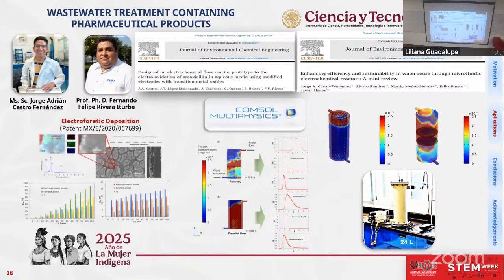So additionally, the title of my presentation is to involve modified surfaces. You can see here how we construct these surfaces, including iridium dioxide and tantalum pentoxide. The iridium is the electrocatalyst to remove the different organic molecules, and the tantalum pentoxide is important to promote protons close to the surface. When we promote protons close to the surface, it generates more oxidant agents like hydroxyl radicals. It's actually very important in the different treatments.